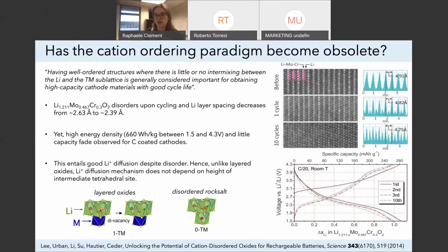3 of them are lithium, and 1 is a transition metal, which is why we call this a one transition metal channel. This is the normal path for lithium diffusion in layered compounds, which very much relies on the size of this tetrahedron. In the case of disordered rocksalt compounds, now you have disorder, and so you can have these tetrahedral sites that are surrounded only by octahedral lithium sites.